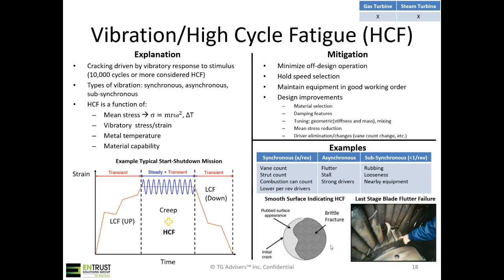The one thing that's really indicative of HCF, when you start looking at a failed component, is the flatness of cracks. A lot of times your crack will be very straight, whereas like we talked about in LCF, it'll be very jagged. The other thing is when you start looking at the micrographs of the surface, you'll see a smooth surface because the surface has kind of rubbed itself smooth. Whereas again, in LCF, you'll see the beach marks.